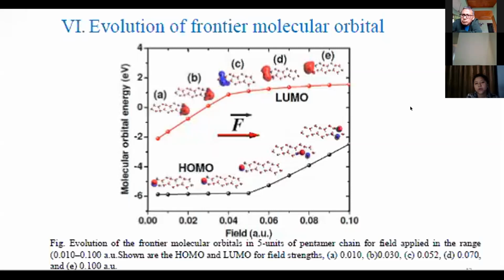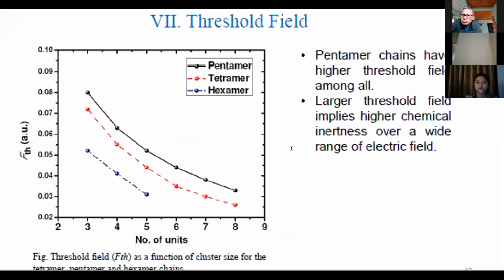Now, as we saw, there is a particular field value beyond which marks the onset of the closure of the HOMO-LUMO gap, and the higher the threshold value, the more chemically stable the system is. So here we have plotted the threshold field values with respect to the number of units. Here we see that the threshold value for the pentamer chain